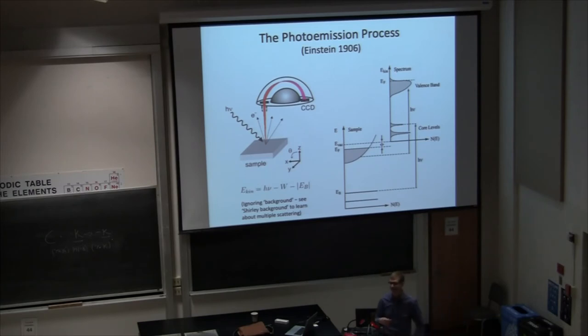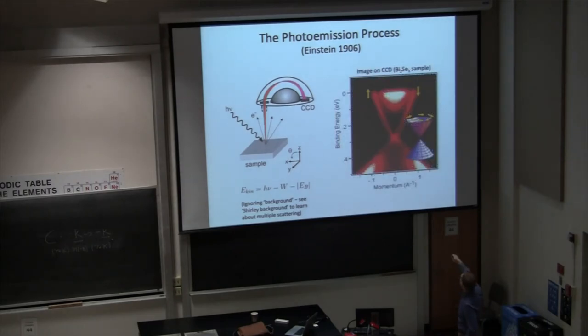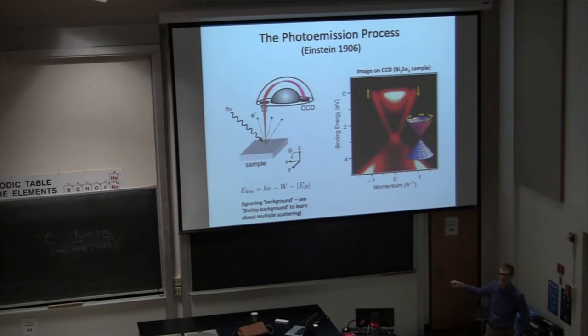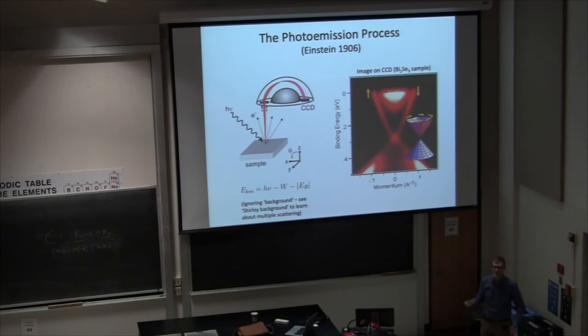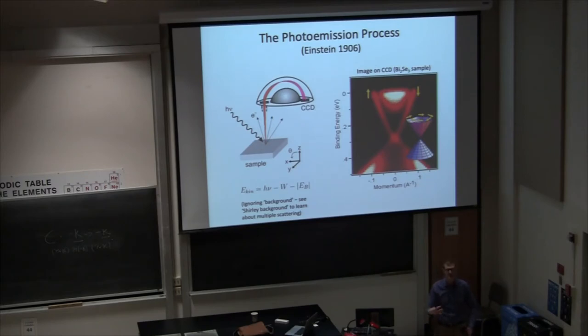The Fermi energy is determined because you don't see any electrons above it — this is what we see on the detector after counting for a long time. Here's a band; it just seems to stop where it hits the Fermi level. We would love to see the band continuing above the Fermi level, but there are no electrons to knock out of the material. At the end I'll show you that with pump-probe ARPES — or by throwing electrons in instead of taking them out — you can actually see states above the Fermi level.